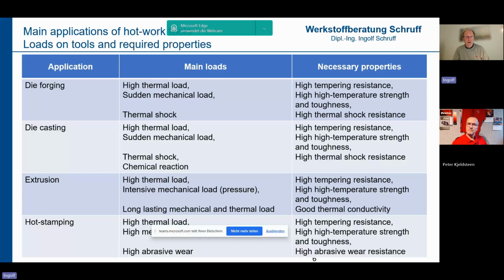So then you better select a steel material with higher carbide content than a standard grade like 1.2343. Then maybe you use a steel with 7% chromium and a little higher carbon content. That still does not develop primary carbides, but it develops a high volume of secondary carbides and provides then sufficient wear resistance.